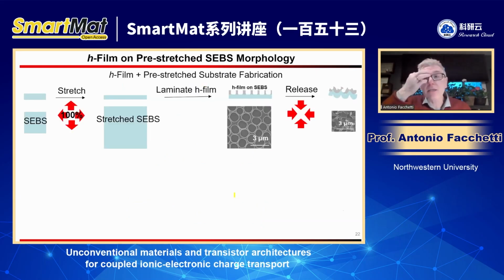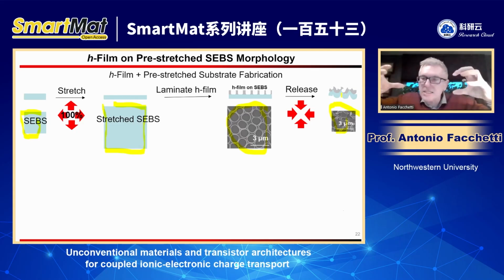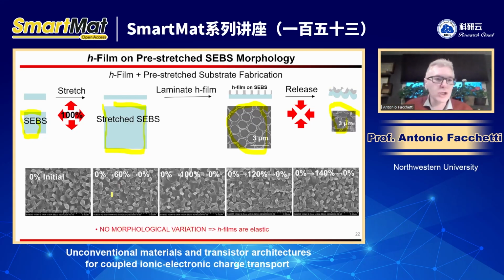Let me explain this a little better. Basically, we take a substrate and we stretch it. For example, here it is stretched 100%, so you double the area of the substrate. Then you laminate the honeycomb film on top here, and then you release everything. Because the substrate is released, the PDMS or the SEBS elastomer goes back, and everything gets crunched. This is how the morphology of the film looks in this position, before. And then we start stretching this pre-stretched film and we release it.